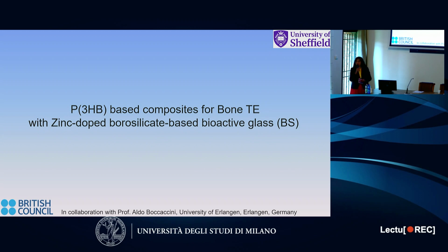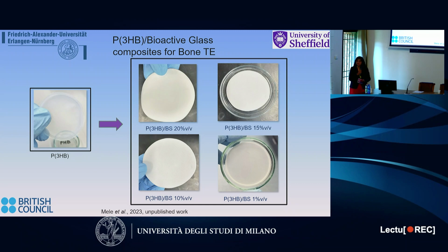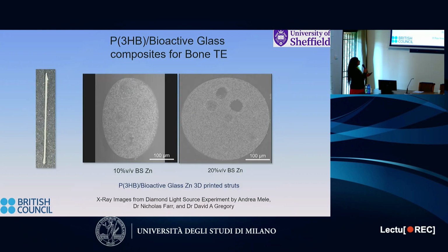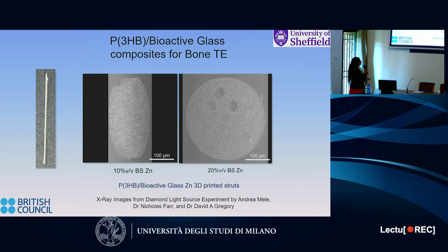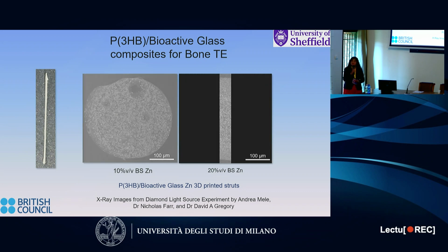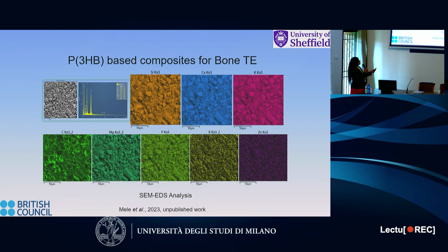I move on to another example, bioactive glass. I'm sure you've heard about these glasses. This is a zinc-doped borosilicate-based bioactive glass produced in Erlangen in Professor Boccaccini's lab. And we created composites of this with P3HB with different volume percentages. We saw that the composites that were formed were very uniform, with a nice distribution of the filler. We also looked at the presence of the various elements using SEM-EDS, and we saw all the elements that we expected to be present in the composite.